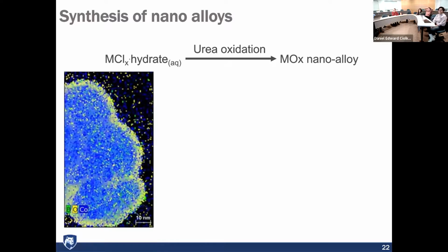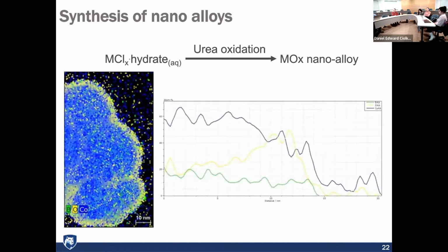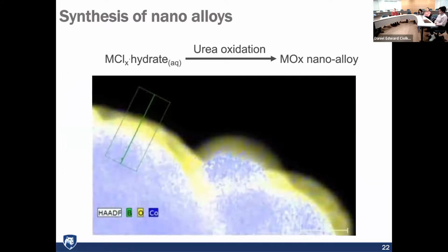It's very challenging. Here we have another TEM image. So here's our nanoparticle, and this one's one of cobalt. You can see that there's cobalt metal on the inside, and on the surface, there's cobalt oxide. So it's got this oxide layer on the outside. And these are just more images of that phenomenon. Again, you can see cobalt here and this oxygen layer on the outside.